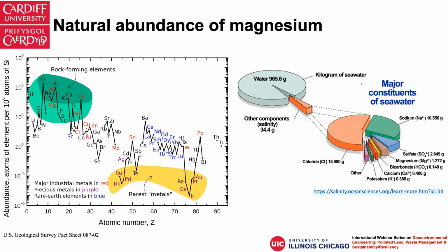While for the magnesium element, you can see from the left figure that it's quite similar. The abundance is almost at the same order of magnitude compared to calcium, which is the main element in Portland cement. On the right-hand side, you can see that the magnesium content in seawater is almost 3 times higher than calcium. So theoretically, there are almost unlimited resources of magnesium that we can use on Earth. But in reality, this is a totally different story.